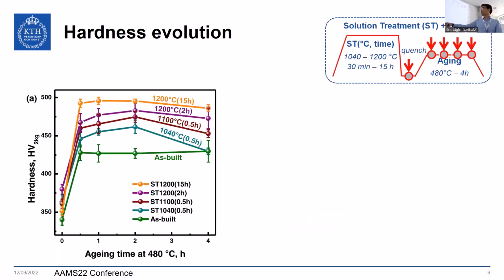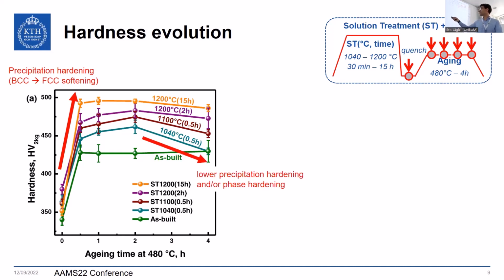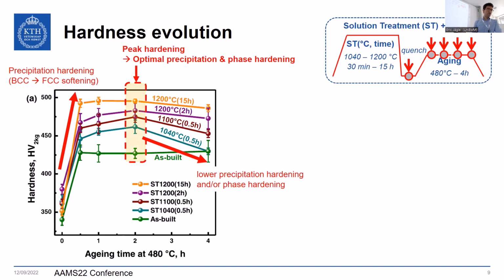So in terms of hardness evolution, here I plot the hardness of all our solution-treated alloys as well as the as-built state over the aging time. So here is the as-quenched material or as-built, and after following aging, right? Yeah. So we see that first we have quite a strong increase of the hardness at the first stage of the aging, which is very likely due to the precipitation hardening, so the precipitation of these nano precipitates of copper, and because this BCC to FCC transformation would only have a softening effect, right? At the very end, we have a lowering of the hardness, which could mean that the precipitation hardening is not optimal anymore, or also that we have some phase hardening decreasing. And we have more or less a peak hardening, so optimal precipitation and phase hardening, after 2 hours of aging.